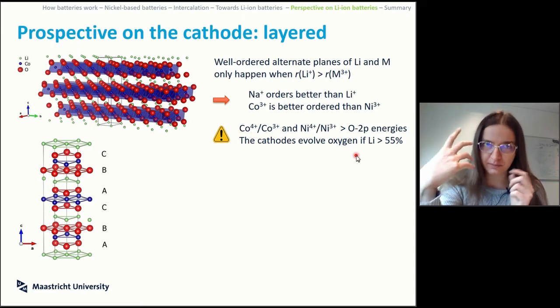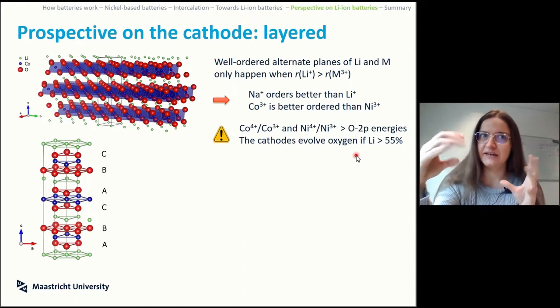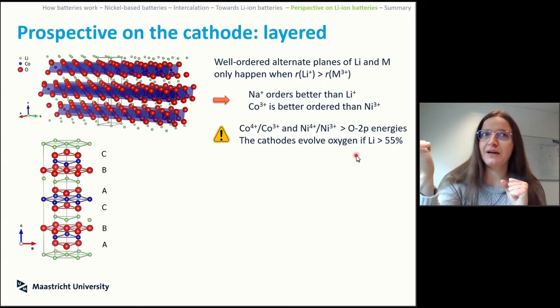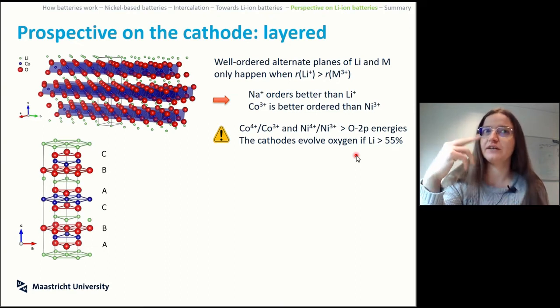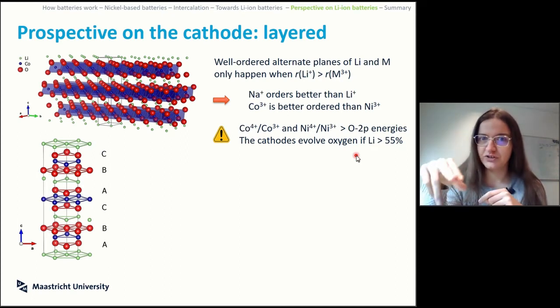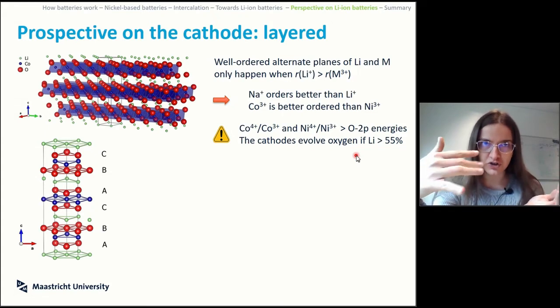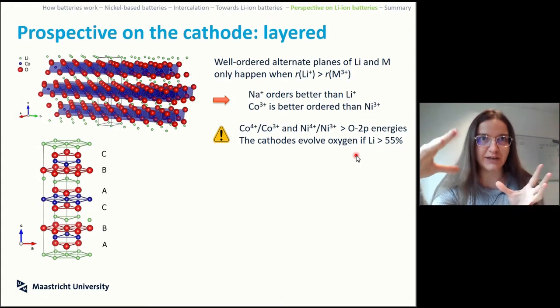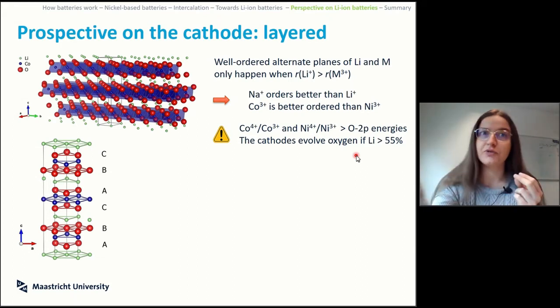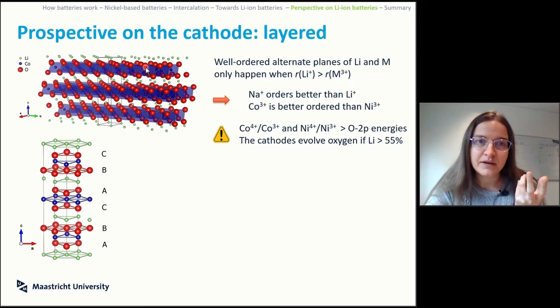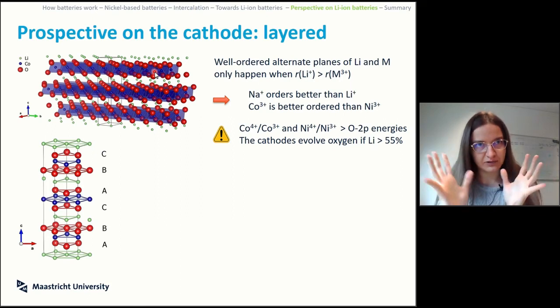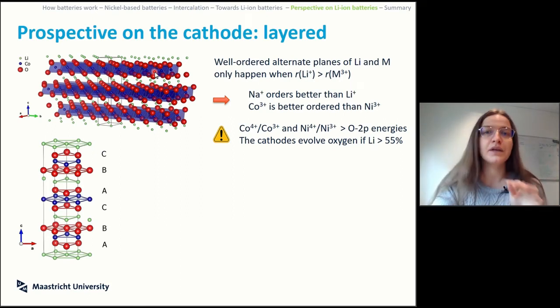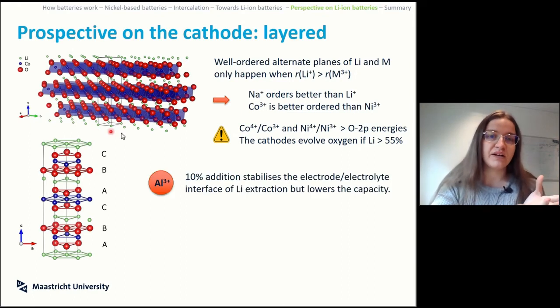If by electrochemistry, by the voltage, your oxygen 2p top band becomes the one that is in chain with this whole series of electrochemical potentials, you will evolve oxygen. So your battery, instead of doing electrochemistry of intercalation and deintercalation of lithium, where as the lithium goes in and out you create electrons, will start to react away the structure and make these oxygens clamp together and go out as oxygen molecules. Not ideal. This can be stabilized if you put in something like aluminum 3 plus.